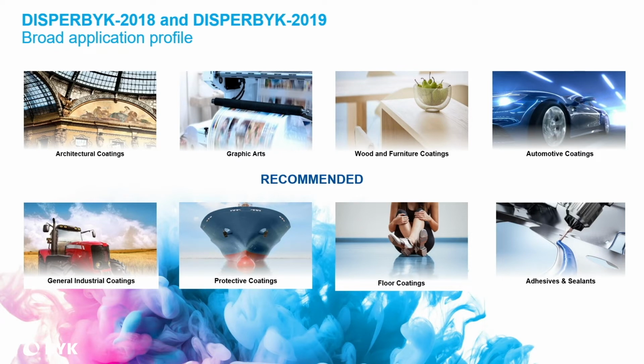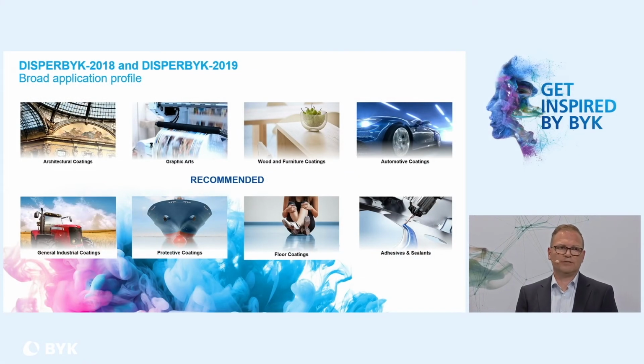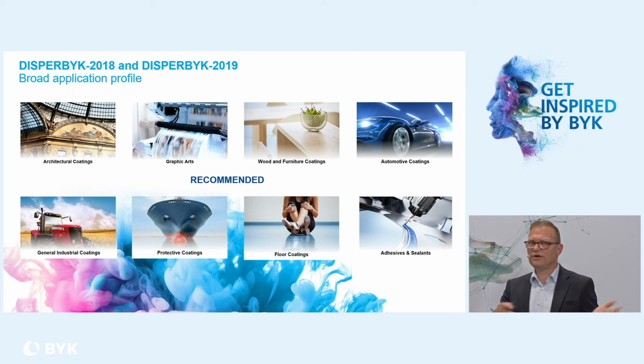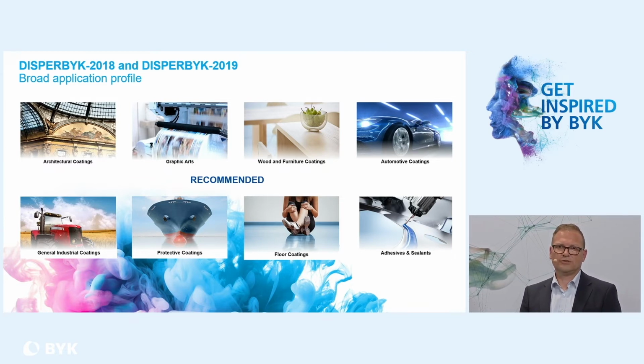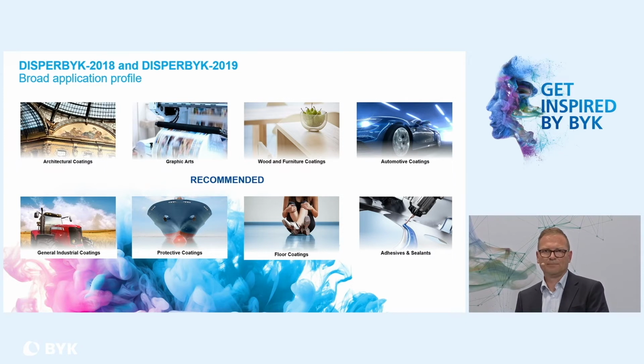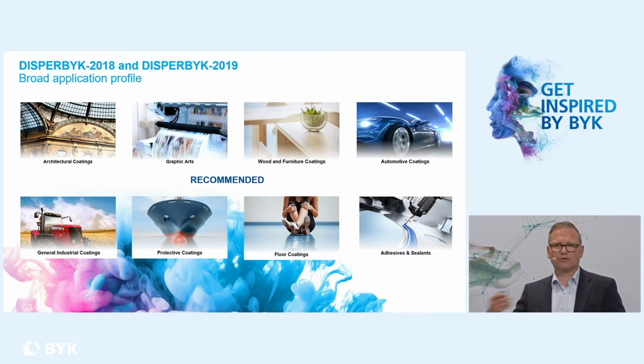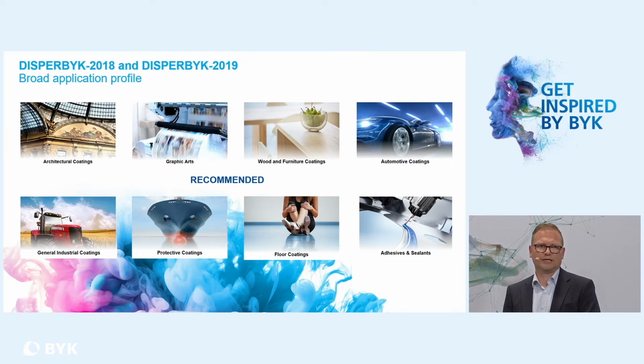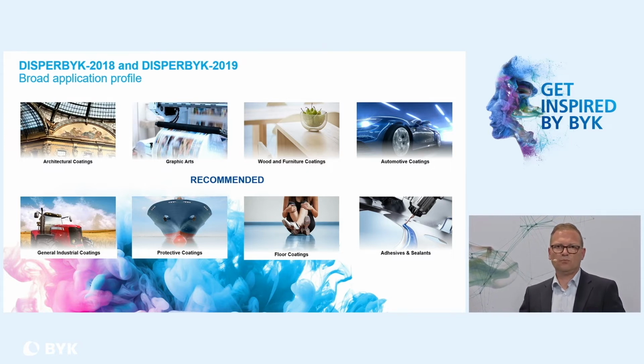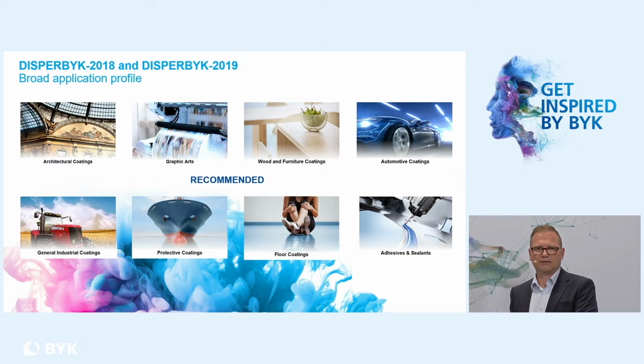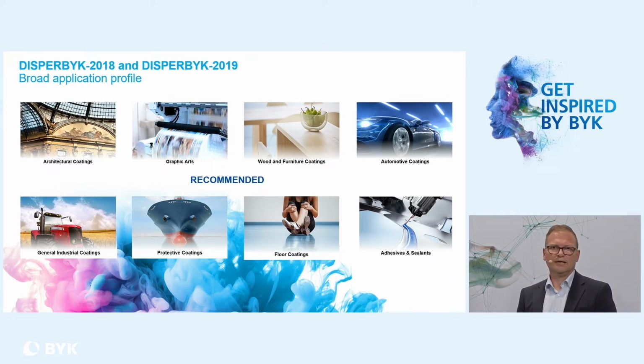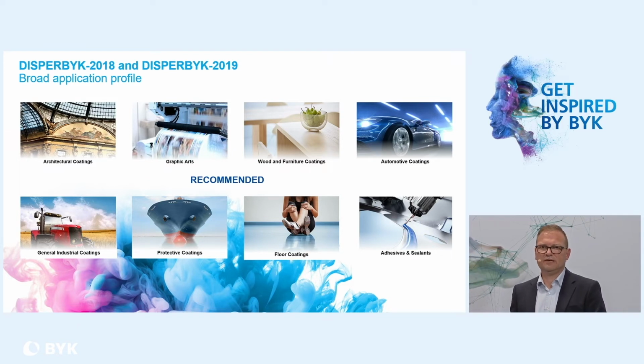In automotive coatings, we achieved excellent results in the slurry production. I showed you the example of a general industrial coating formulation. Remember the 2-pack PU, the green one, with high color strength development, high gloss levels, and low delta E values. Protective coatings, remember the water-based epoxy primer with minimized side effects, so better corrosion protection for your marine and protective formulations. In floor coatings, water-based epoxies, 2-pack water-based epoxies, you grind usually in the amine part, so again at higher pH values. And also here we find excellent results and a good storage stability. And last but not least, even in adhesives and sealants to grind your filler particles in the formulation, again, very good results.